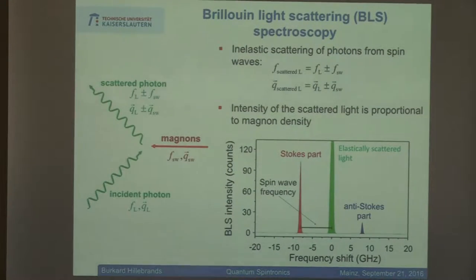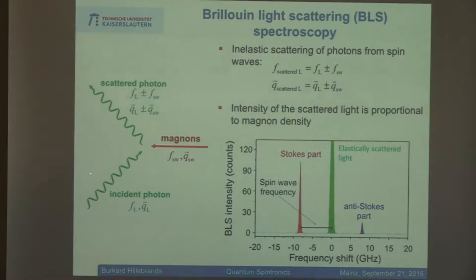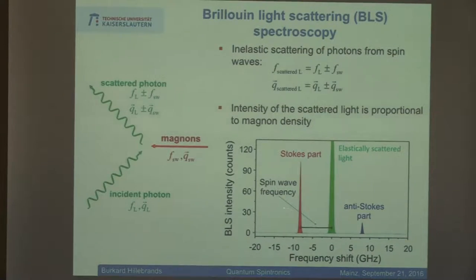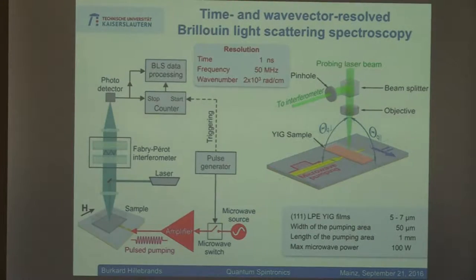Before I continue, let me tell you how we measure that. We have the method of Brillouin light scattering, which turns out to be extremely versatile for studying these phenomena. The idea is simple: we use photons from a laser — single frequency, monochromatic photons — and they are scattered by the magnons. In second quantization language, either a magnon is created or annihilated, and the scattered photon carries away that information. By measuring the scattered photons we know the frequency and the wave vector of the magnon. The frequency appears as a frequency shift in a spectrum using a spectrometer, and the intensity tells us about the population of these magnon states.